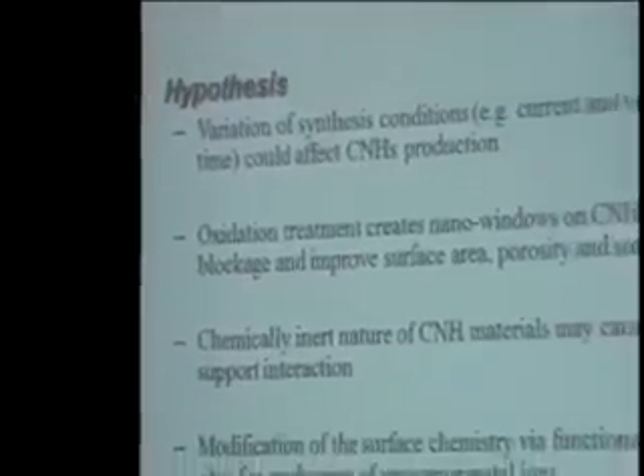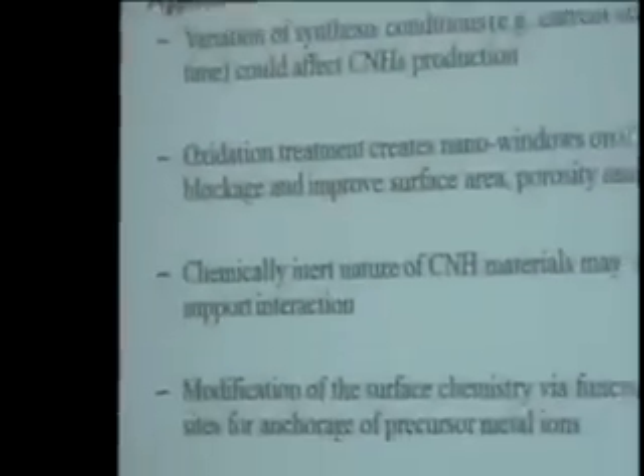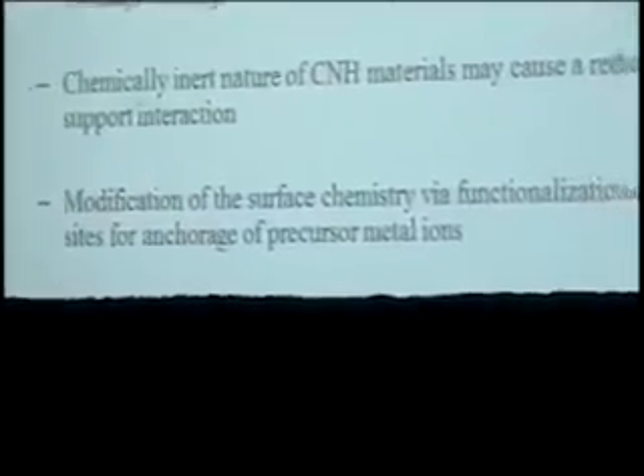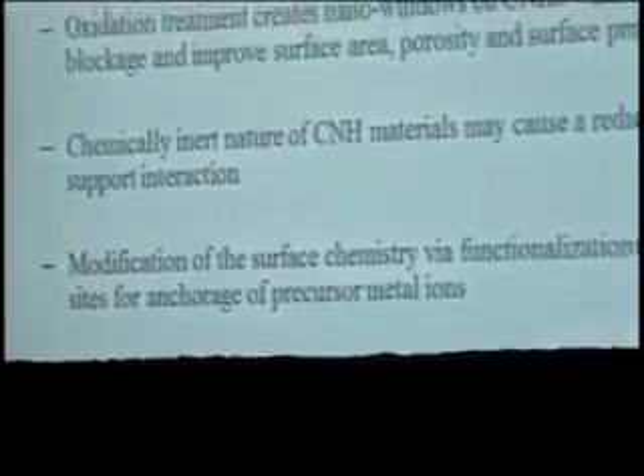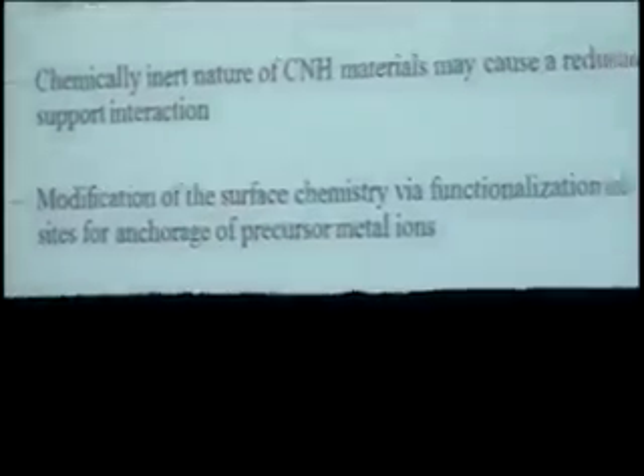In terms of hypothesis, we expect that variation of synthesis conditions like the current, voltage, and electrode dimension could affect the CNH production in terms of quality, the amount, and the type. And the oxidation treatment could create nanowindows in the carbon nanohorns, which would help to eliminate pore blockage and improve the surface area, porosity, and surface properties of the carbon nanohorns. The chemically inert nature of carbon nanohorn materials may reduce the strong metal support interaction as compared to gamma alumina. Also, modification of the surface chemistry via functionalization of carbon nanohorns will provide sites for anchorage of the precursor metal ions.